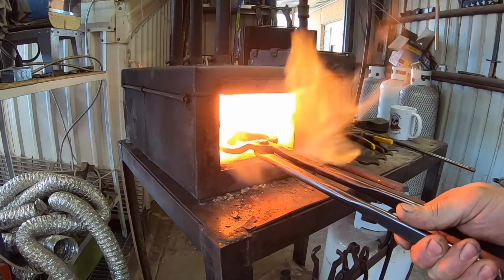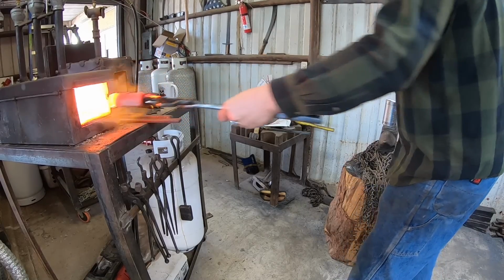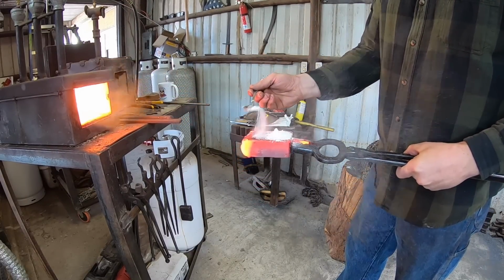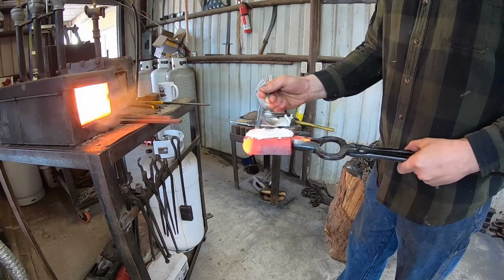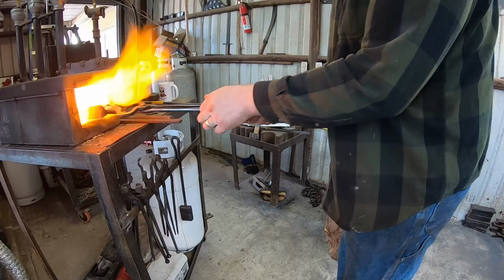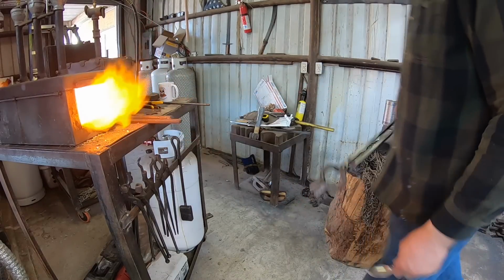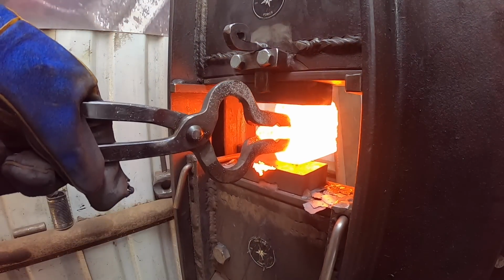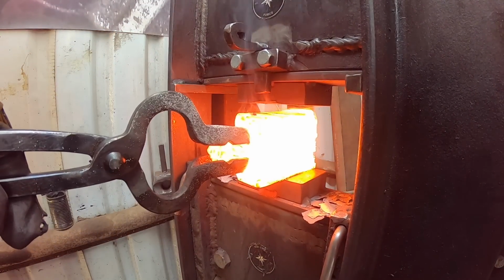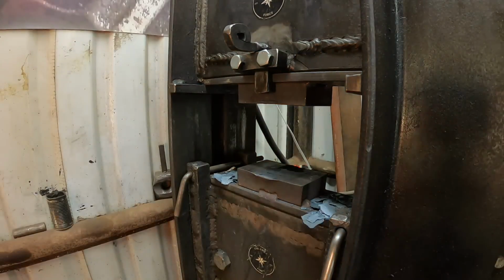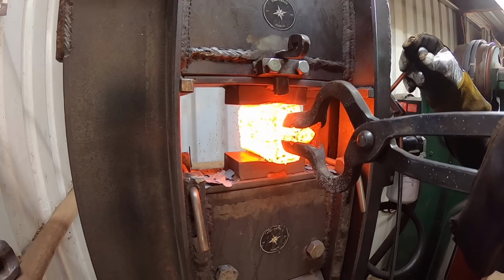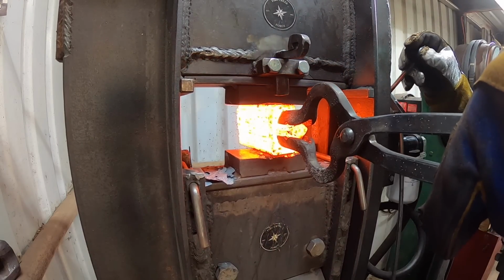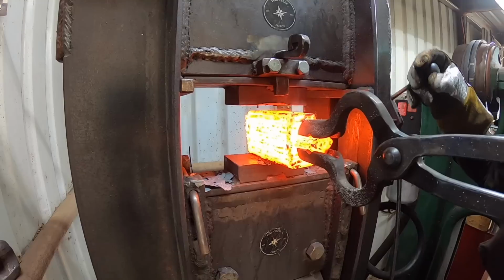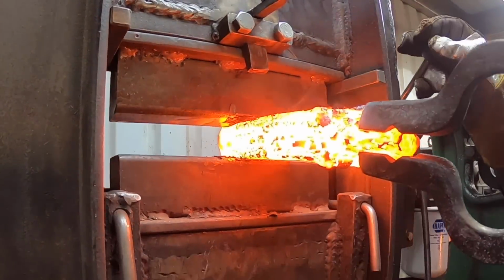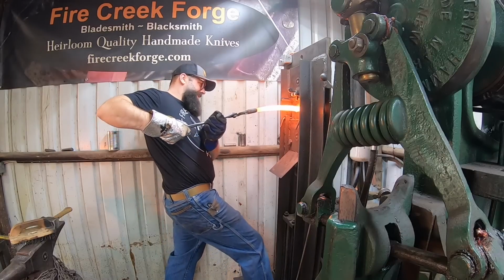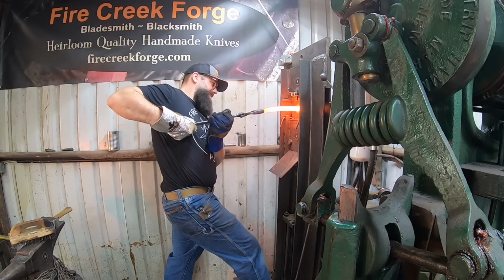So there we've got our billet all assembled, and I've arc welded the ends, or the sides at the ends, just to hold everything together. The WD-40 that I'm spraying on there aids in the forge welding process, and we can go ahead and set the weld in the forging press. This went together quite nicely, and I was able to forge it out into another long bar.